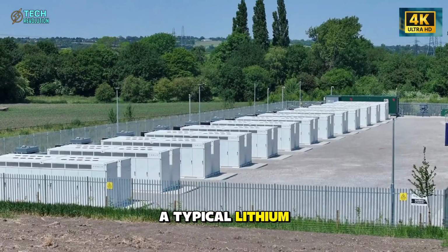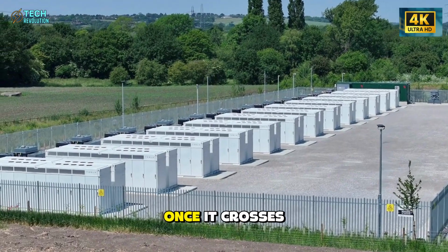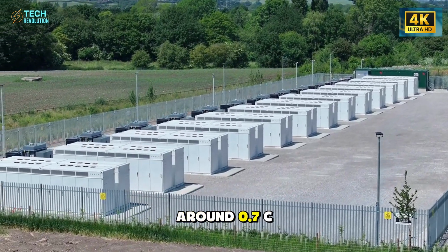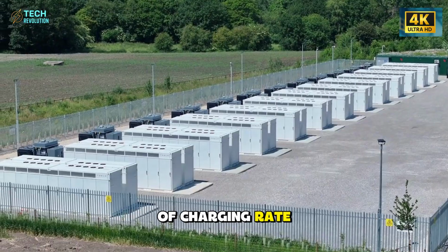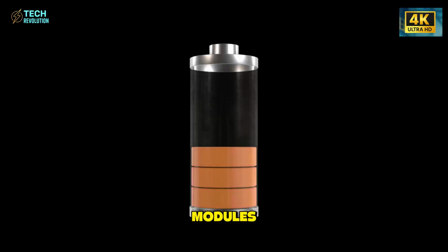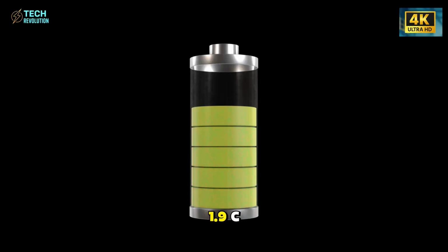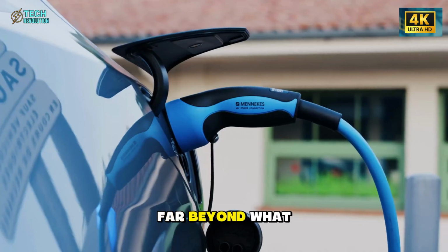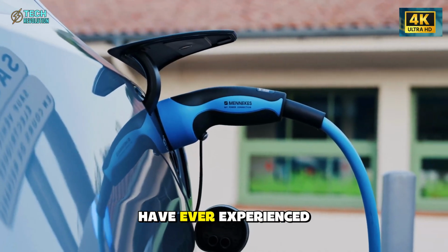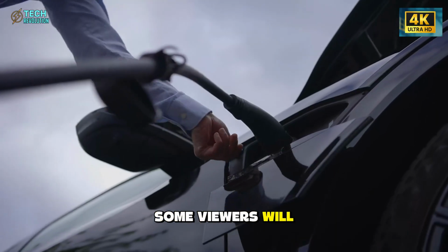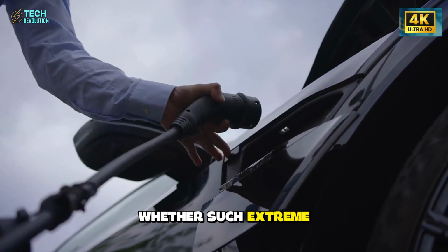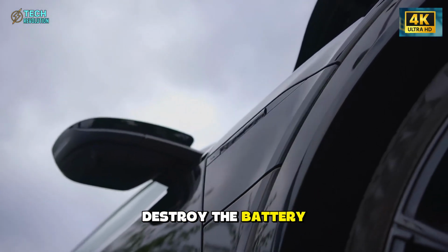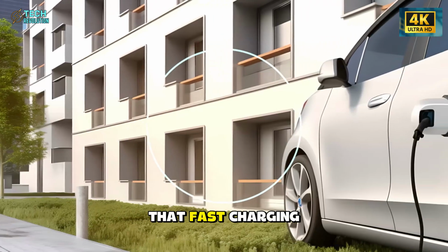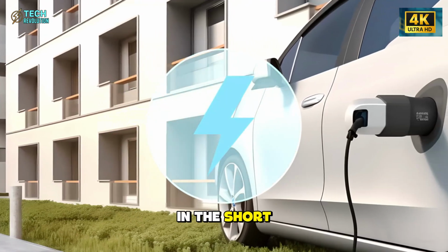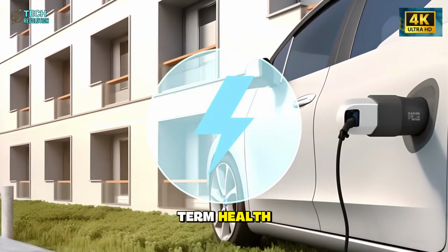A typical lithium pack begins to protest once it crosses around 0.7C of charging rate. The aluminum-ion modules comfortably reached nearly 1.9C, far beyond what most EV owners have ever experienced. This is where debates start. Some viewers will immediately question whether such extreme charging speeds destroy the battery. Others will argue that fast charging only looks good in the short term, but crushes long-term health.